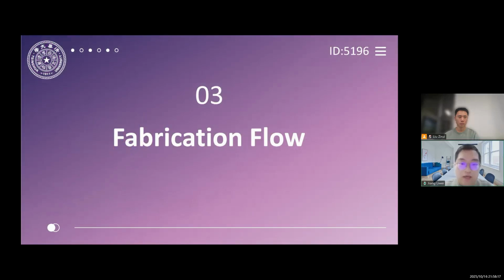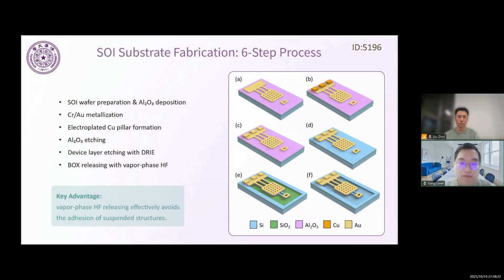Now let's take a look at how we actually build these things. Starting with the SOI side, we use a 6-step process. First, we begin with SOI wafer preparation, followed by aluminum oxide deposition. Then we do chromium and gold metallization to form the contact layers. Next, we electroplate copper pillars. These will later be used for bonding. Then we etch the aluminum oxide using the metal as a mask. No extra photolithography needed here.